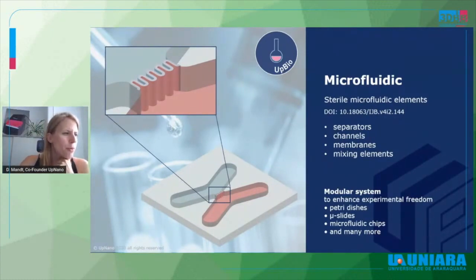When finishing the print job, there is no post-treatment necessary, so no UV post-curing or things like that have to be done. The only thing you have to do is wash away the unpolymerized material, and this is done with an alcohol-based solution. In most cases, it's an isopropanol-based solution that is used to wash it away. And then the structures can be used and further processed.